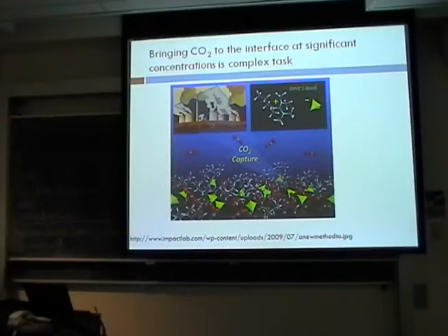So I think I took this from an ionic liquids paper. Ionic liquids are, as the name implies, pairs of ions that still can freely move about as liquids can. And the fact that these are charged actually makes them very good for having Lewis acid-base interactions with carbon dioxide and therefore capturing it and potentially bringing it to the surface. So people are just starting to study how some of these strange solvents interacting with surface reaction species might affect how the CO2 reduction to fuels reaction would occur.